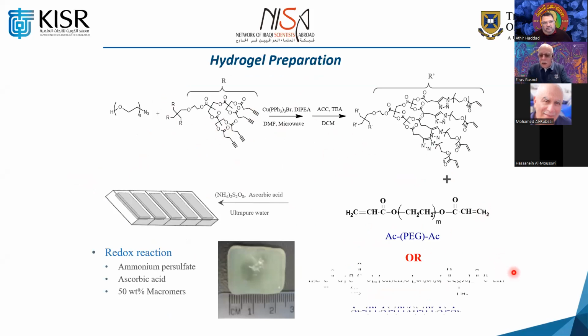We used it in conjunction as a copolymer with diacrylate, polyethylene glycol diacrylate, to make a hydrogel. As well as we used it with a tri-block copolymer. We synthesized the tri-block copolymer with PLA, polylactic acid, with polyethylene glycol. And of course, we prepared a variety of these with a shorter chain, a longer chain, very long chain, in order to evaluate how this is performing as a hydrogel with this nanoparticle we made. So we cross-linked it all together.